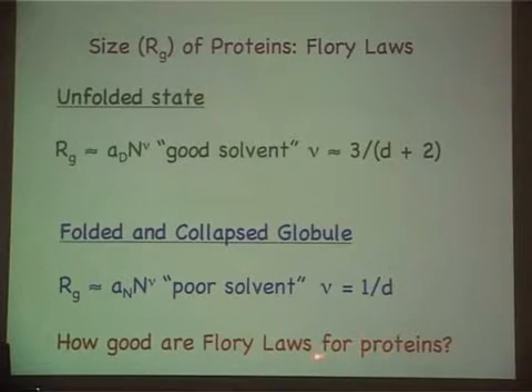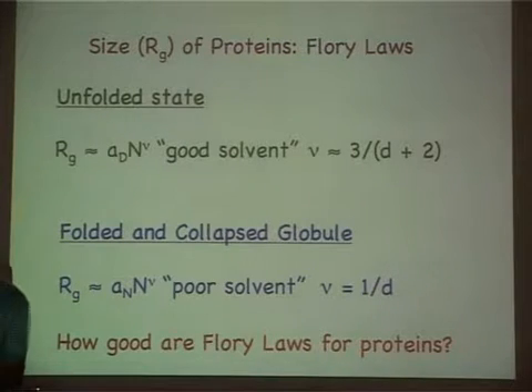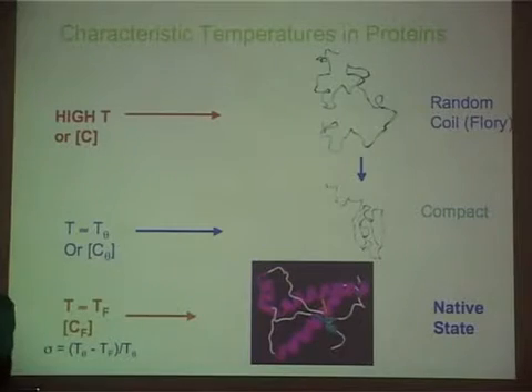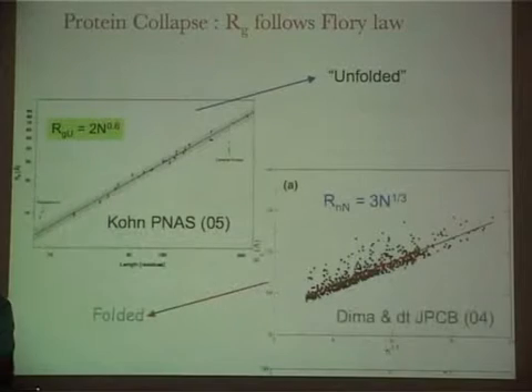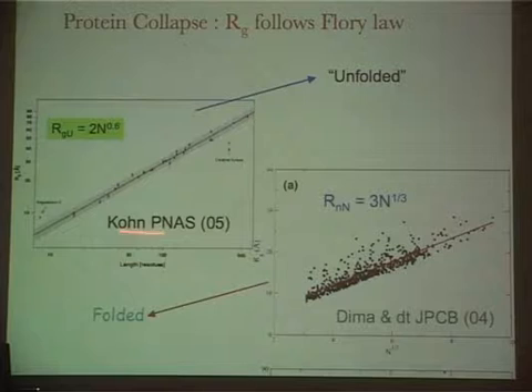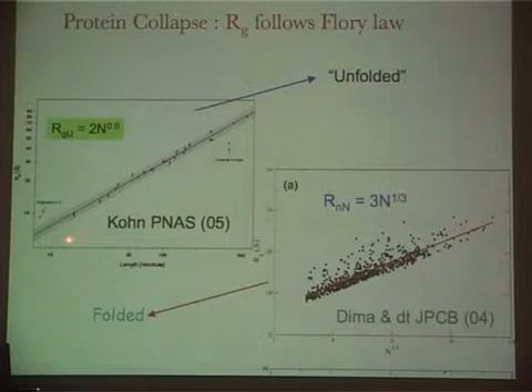So how good are the Flory laws for proteins? That will answer the question about what these prefactors are, and I'll also tell you some numbers associated with the persistence length. So these are experiments in a log-log plot done for unfolded conformations, generated largely by denaturants, but sometimes by temperature. And it turns out that for the unfolded state, you can fit this as 2 angstroms times N to the 0.6. The 2 is a very small number.